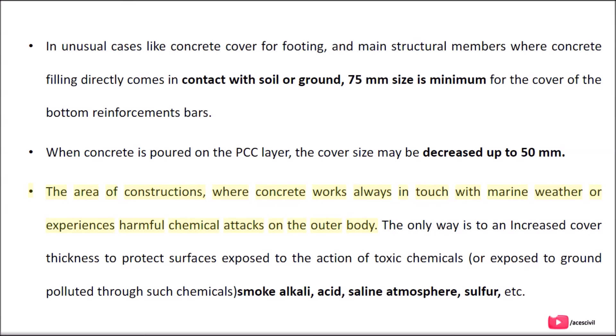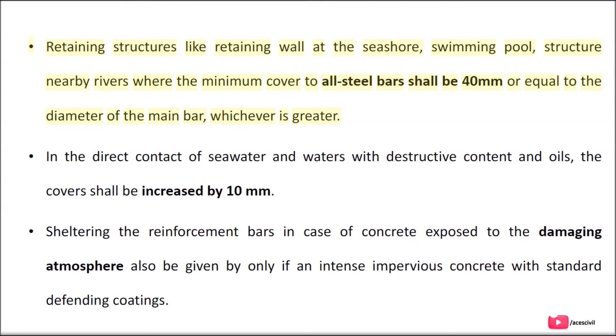In areas of construction where concrete is always in contact with marine weather or experiences harmful chemical attacks, the only way is to increase cover thickness to protect surfaces exposed to toxic chemicals, ground polluted by such chemicals, smoke, alkali, acid, saline atmosphere, sulfur, etc. Retaining structures like retaining walls at the seashore, swimming pools, and structures near rivers require the minimum cover to all steel bars to be 40 mm or equal to the diameter of the main bar, whichever is greater.